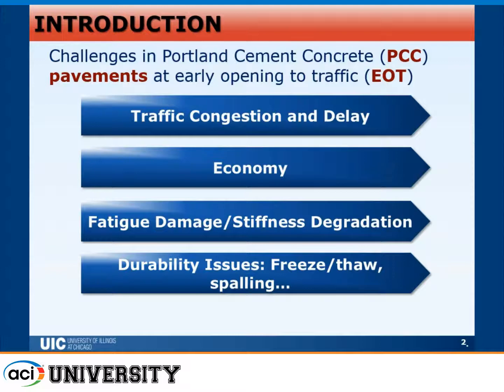And for example, for PCC pavement mix designs, I'm going to go over them in a little bit. The criteria for opening to traffic is compressive strength exceeding 3,500 psi. And it will also be covered, part of it, in the next presentation, that we can also add into these parameters another parameter such as the effect of stiffness degradation due to early loading at early age of the